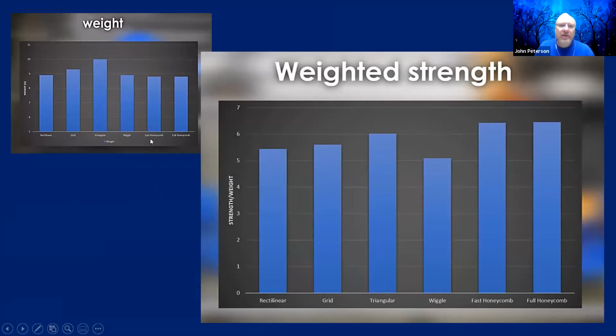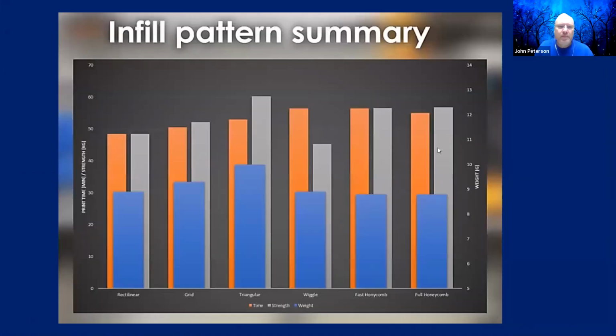And when this was examined, I found out that, for instance, from the left side of weight, you can see that the triangular one actually weighs more. These are all supposed to be 35% infill, but analysis showed this was about 45%. So again, these things can vary a little bit. But the important thing is the weighted strength here, that takes that into account. And you can see that the honeycomb ones tend to be a little bit stronger. It's not dramatic, and you'll have to decide if the extra time is worth it. But that particular test shows you what difference in geometry makes there.